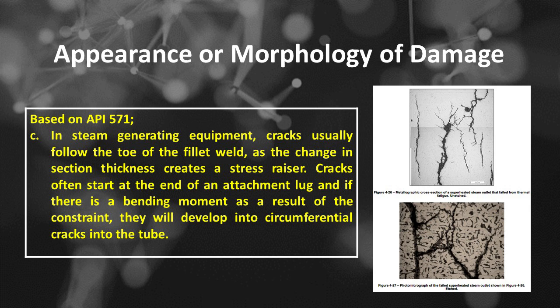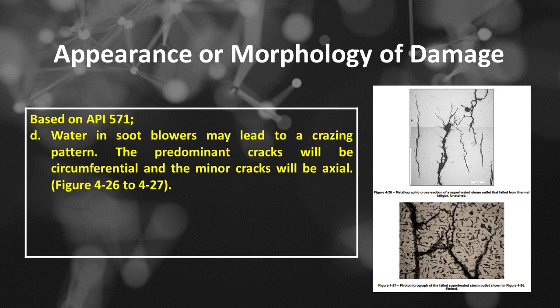The third is in steam generating equipment. Cracks usually follow the toe of the fillet weld, as the change in section thickness creates a stress raiser. Cracks often start at the end of an attachment lug, and if there is a bending moment as a result of the constraint, they will develop into circumferential cracks into the tube. The fourth is water in soot blowers may lead to a crazing pattern. The predominant cracks will be circumferential and the minor cracks will be axial. See Figure 4-26 to 4-27.